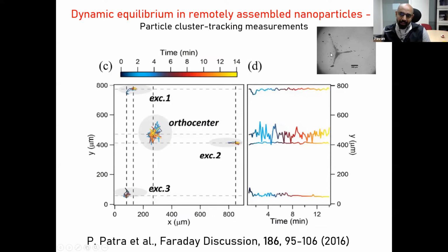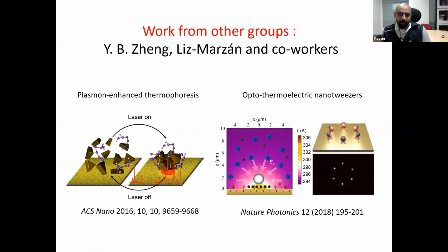And this gives rise to some very interesting concept of active assembly and optothermal assemblies of nanoparticles. We can also do a cluster tracking analysis and look at the fluctuations. And shown here is the fluctuation as a function of time. The orthocenter assembly is very dynamic, meaning there is a lot of fluctuation in that particular region, but there is always some signal coming out, whereas the other ones are all static because there is a field which is already created. Now, going further, people have utilized these kind of techniques also very interestingly. For example, Y.B. Zheng, Liz-Marzán, and various different people.